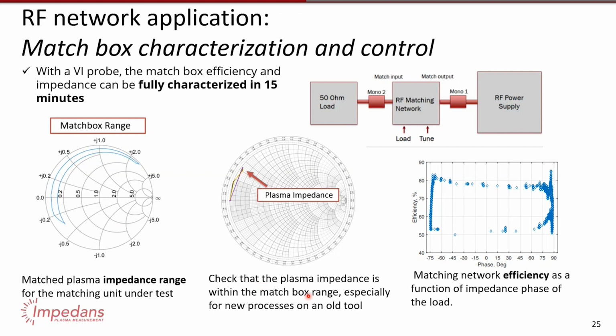And one critical thing is if you're running new processes on old tools, you can't guarantee that your matchbox is still matched to the new plasma impedance. So you may measure the plasma impedance and it's out here, and this matchbox won't reach it. So that means you'll always have reflected power. You'll have common matchbox failures. You'll have matchbox overheating, runaway effects, thermal effects, and so on. So using a VI probe, you can very rapidly map out a matchbox impedance range. You can check the plasma impedance, and then, if you have the capability in-house or you contact your supplier, you can modify the match so that this impedance range moves to match your plasma impedance. We're actually going to send out documents in a few weeks on how to do this mathematically. We'll send out some how-tos on this.